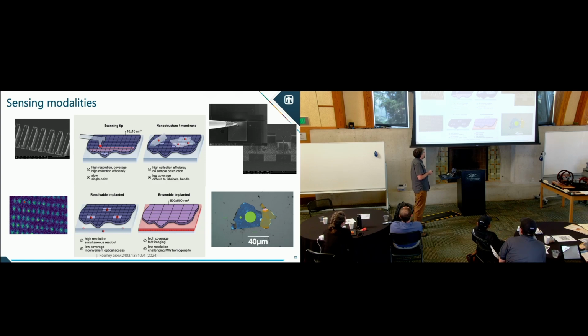All right. Now, if you're not going to be in this scanning mode, you can also do nanostructures and integrate your NV diamond onto materials. So one way is to make nanobeams. You can pick and place them, and actually you can make diamond membranes, which are very thin diamonds, typically about 200 by 200 microns and maybe only a couple hundred nanometers thick. And you can place this on your material of interest and do your measurements. So you can improve collection efficiency, and there's no issue with samples, but the problem is you really have to move them around and put them on there.